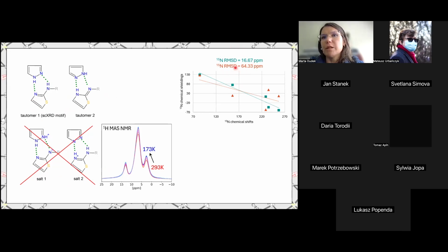We should see something below 6 ppm, 6 or even 5 ppm. But what we noticed is that the points for different nitrogen atoms lie on opposite sides of the trend lines for the two opposite tautomers. So we thought, okay, this seems like averaging of the structures, so maybe we have something in between. A very fast exchange between those two tautomers, so fast on the NMR time scale that we actually see averaged chemical shifts.